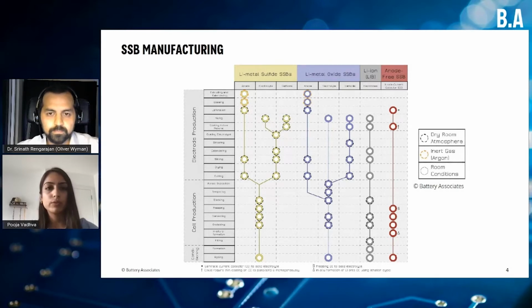So one thing a lot of industry and academia are looking at is trying to develop this anode-free cell. Basically, you wouldn't have to deal with lithium metal foil, which is very reactive and hard to process. You would just electrochemically plate the lithium from the cathode material onto the current collector, forming the lithium metal in situ. And this would again reduce a lot of the manufacturing cost and stages.